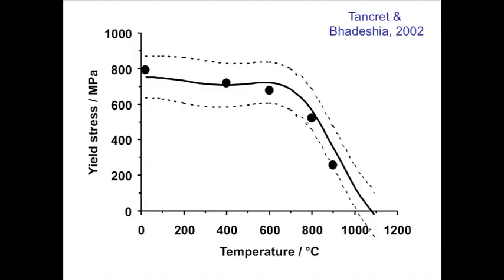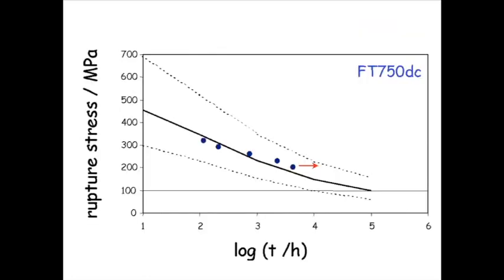This is the microstructure. We have a small fraction of gamma prime. Normal aircraft engine alloys contain almost 70% of gamma prime. And we are interested in the yield strength as a function of temperature. These were the predictions, these are the uncertainties, and these are the experimental results we obtained. And similarly, for the creep rupture test, we've gone up to approximately 10,000 hours. These are the predictions, this is the requirement, and these are the uncertainties, and these tests are still continuing.